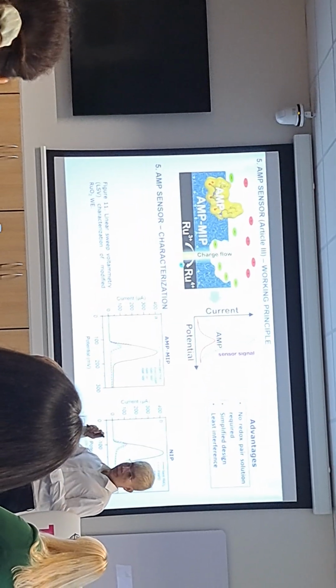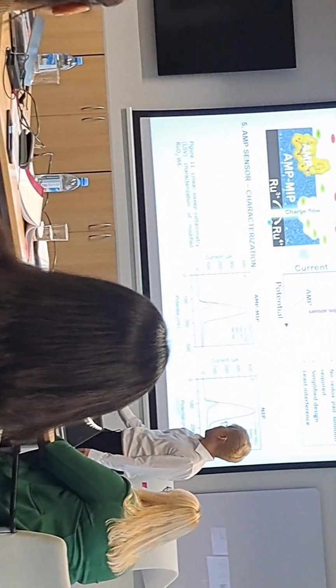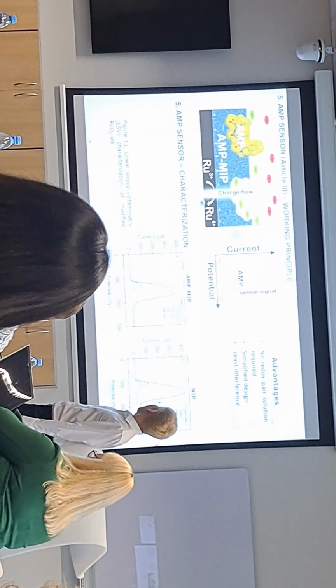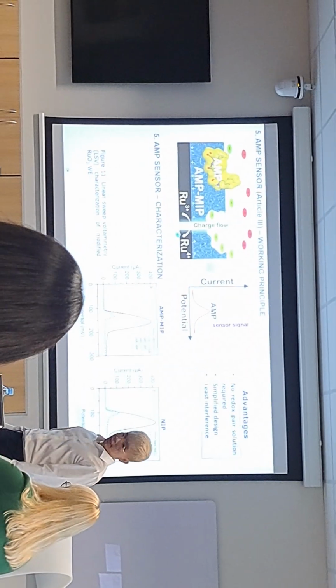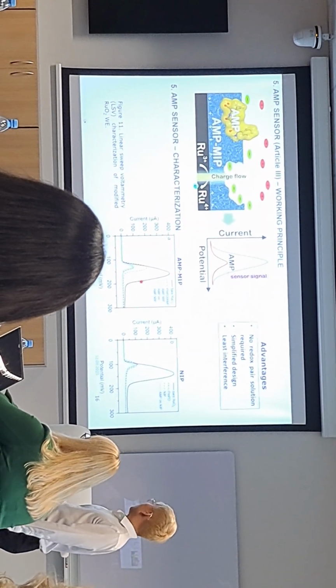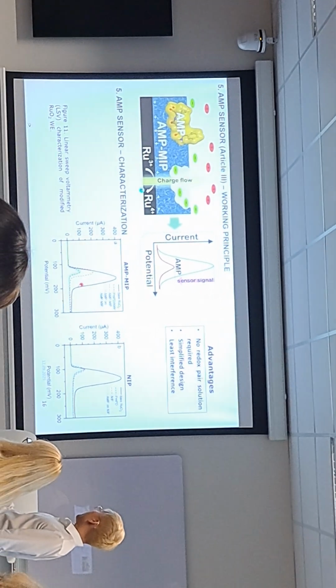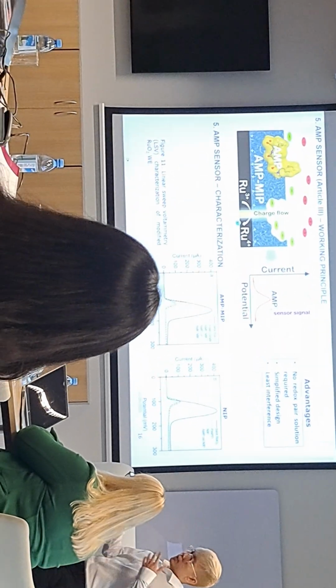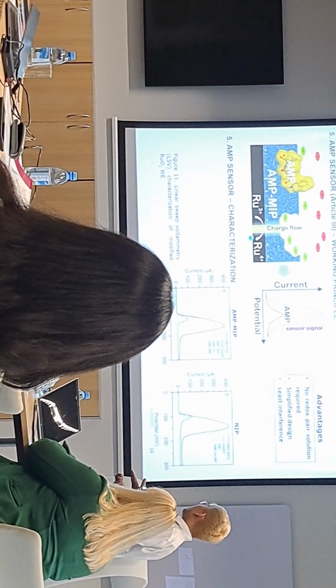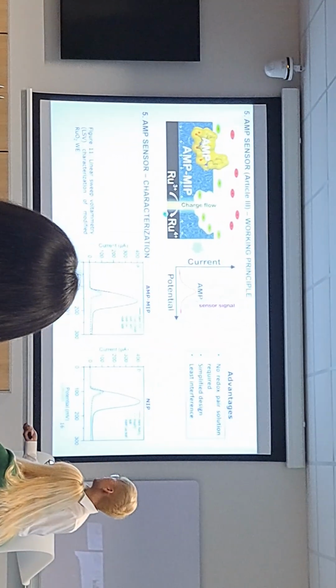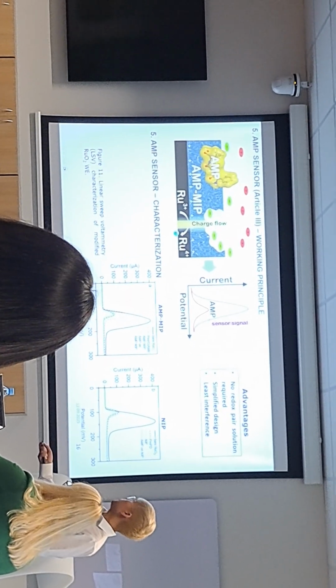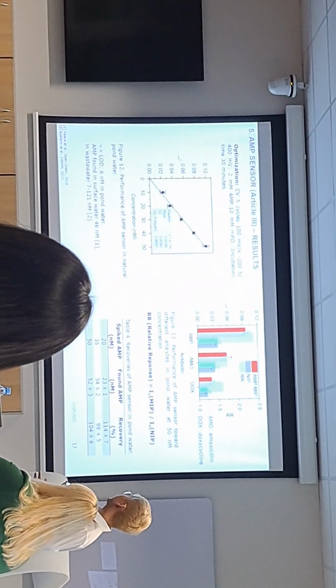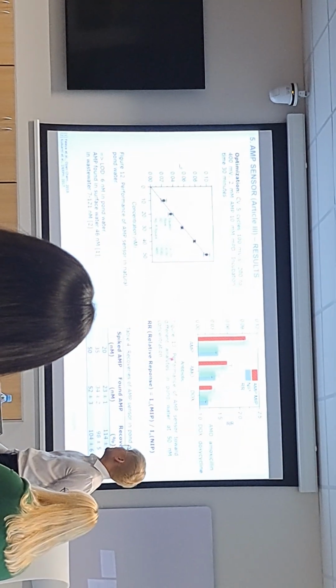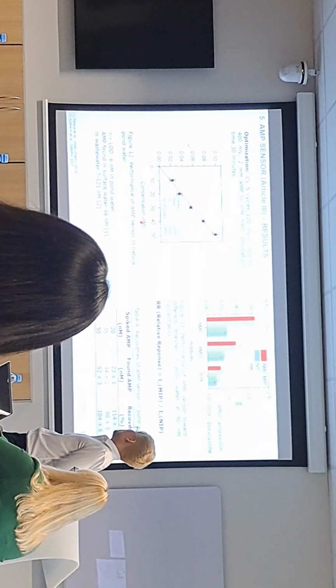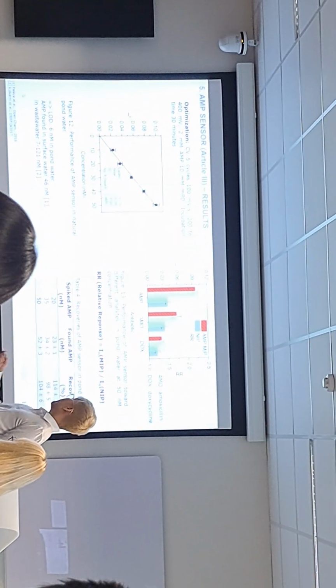This is about characterization. I use the oxidation peak of the CV, the upper part, called linear sweep voltammetry. I measure both for MIP and non-imprinted. The only difference is that after washing out in the MIP material, I see the peak partly recover, similar to previous research. It indirectly tells me that in my MIP material there are some cavities. And after some stages of optimization, I measure low concentrations again to calculate the limit of detection.